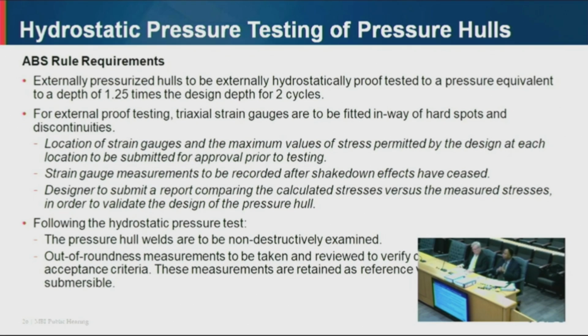And then once the hydrostatic pressure test is completed, you'll have non-destructive examination of the hull. This is done by surface NDE techniques such as magnetic particle testing, dye penetrant testing, or eddy current testing, okay? And then out of roundness measurements are taken, and then we verify compliance with the acceptance criteria in the ABS underwater rules, okay? Now these out of roundness measurements after hydrostatic pressure testing are used as reference measurements throughout the life of the submersible, okay?